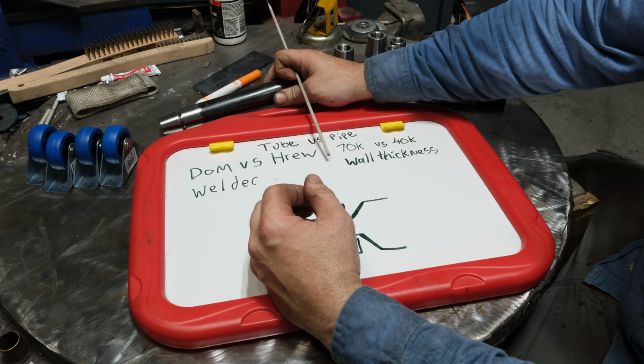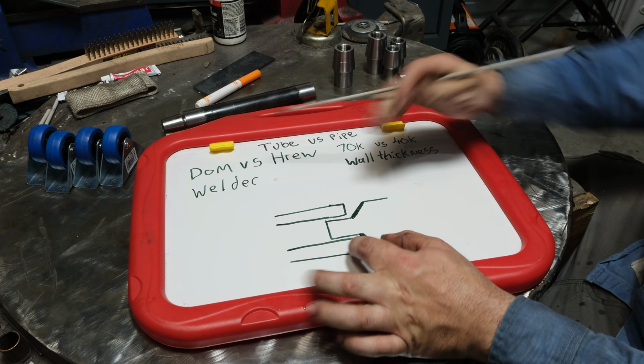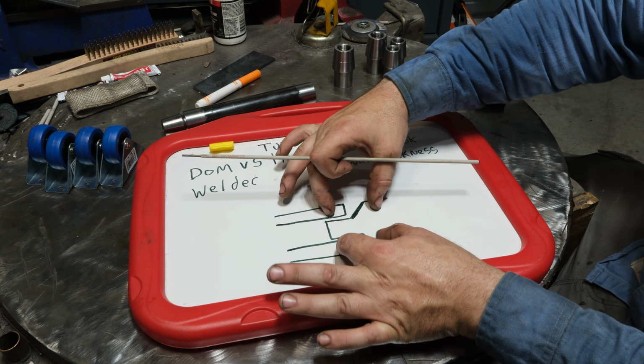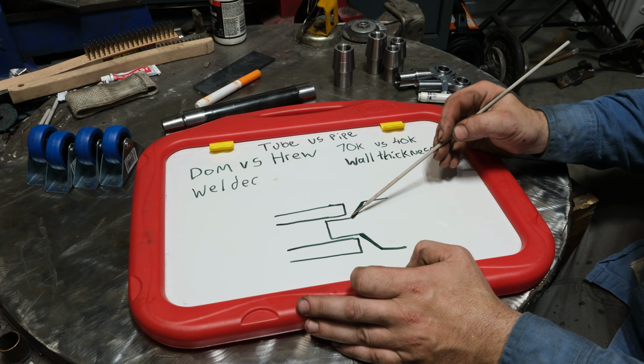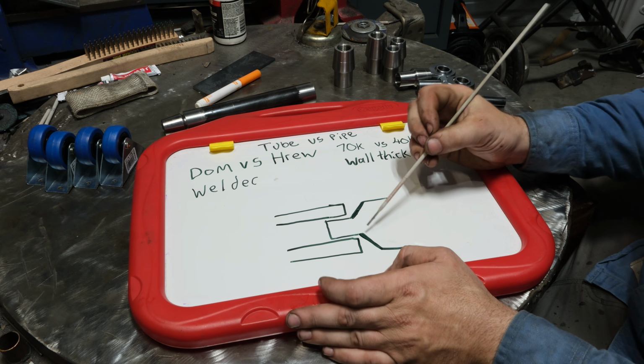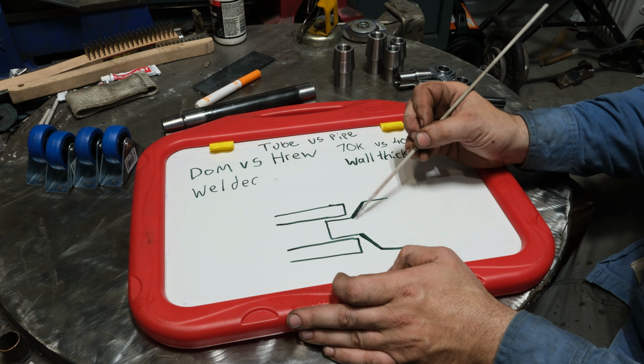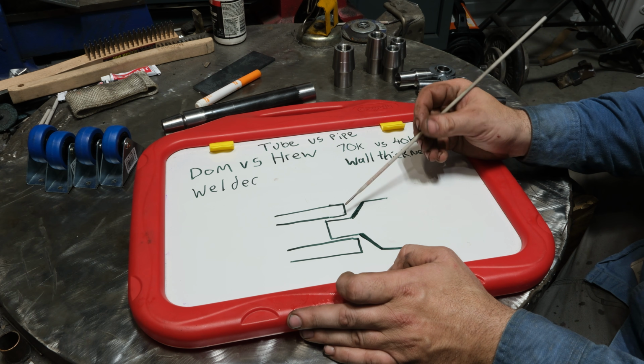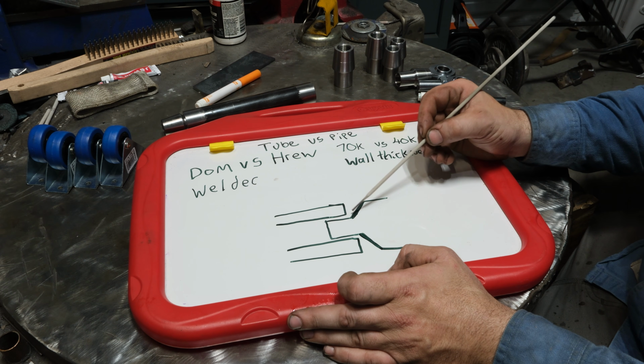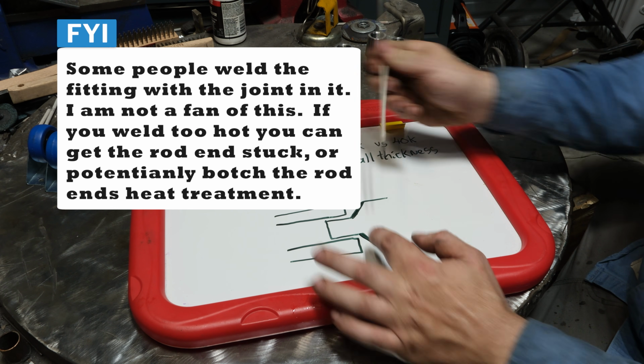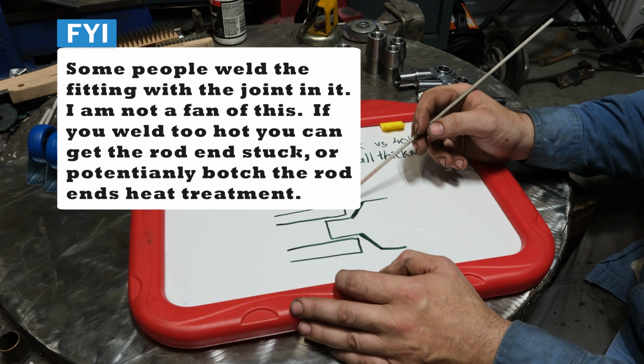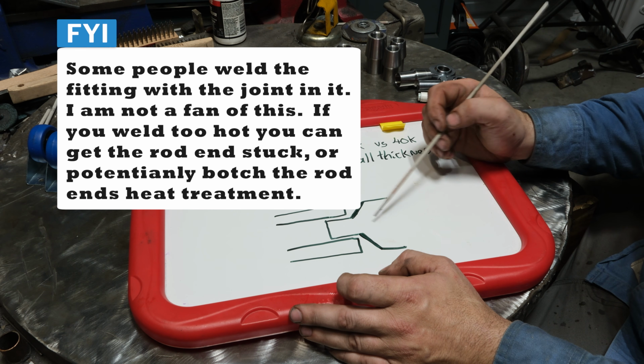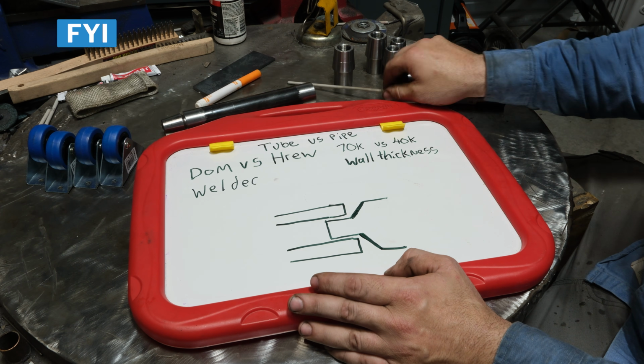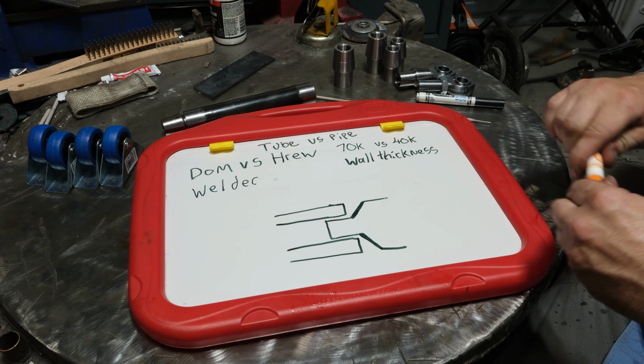What ends up happening is if you jam that in there and weld it, the weld shrinks, pulls these two together, and because you have a tapered fit here, it ends up compressing in this section right here, which then makes it impossible to thread in. By leaving a slight gap in here from this chamfer from touching that, as it shrinks, it's not going to compress that in, and you should be able to thread your Heim joint directly in it without issue. That's something I learned.